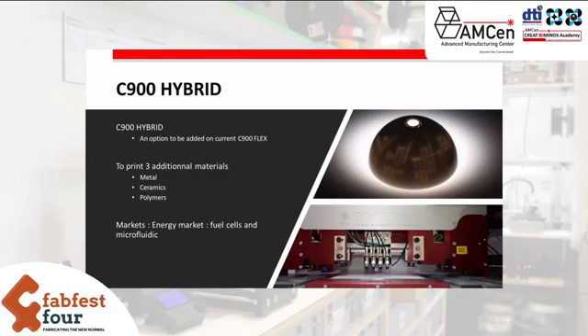We made the choice to develop it with the same process. So we use the same printer with the SLA process for the main ceramic, with a UV laser on the top, and we have 3 specific nozzles in order to deposit the other materials. Before any deposit, we blow the uncured paste in order to remove it and to create a gap. Of course, I will show you some video on the next slide.